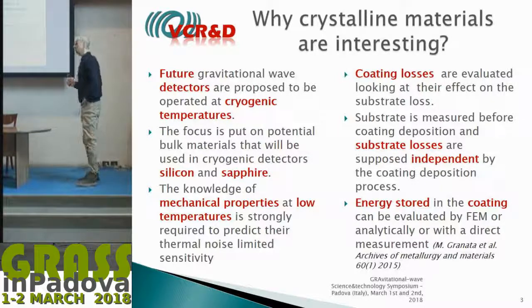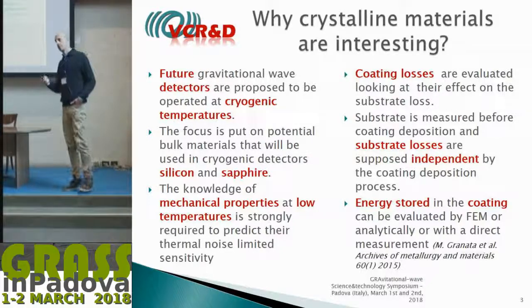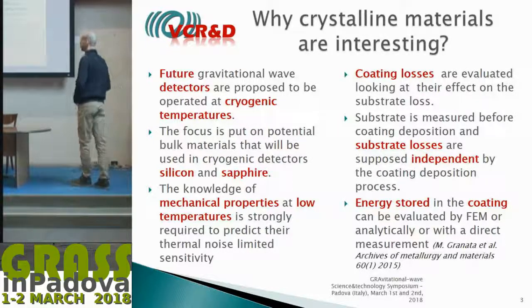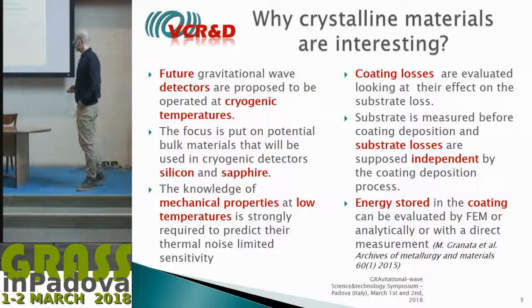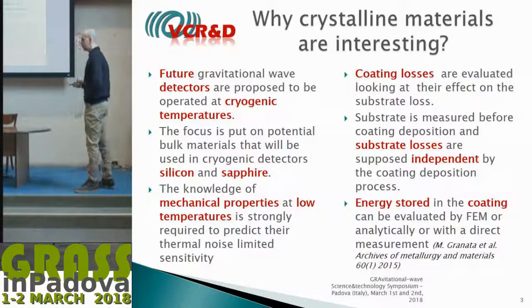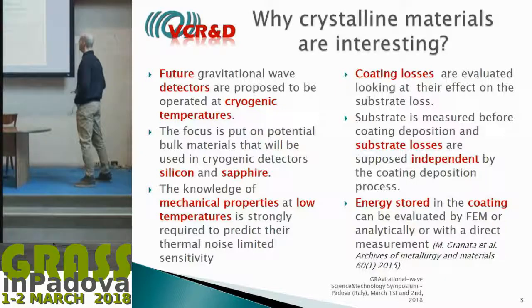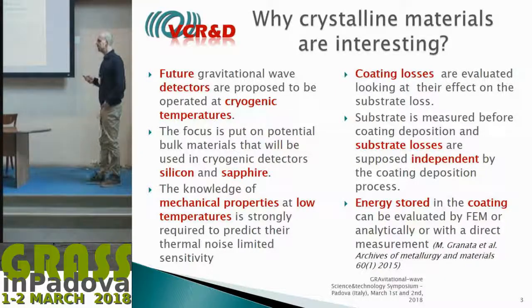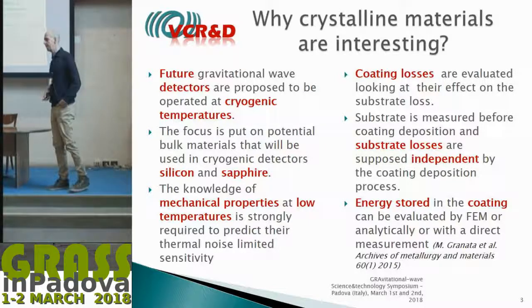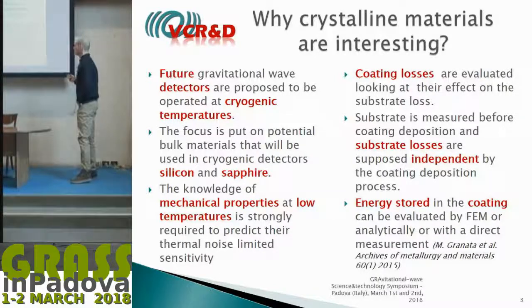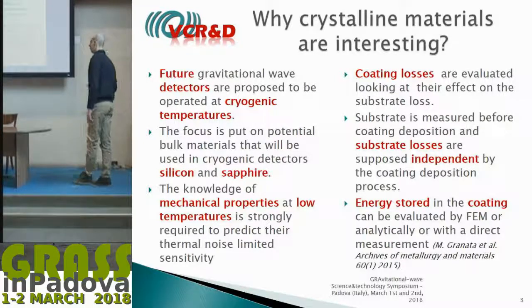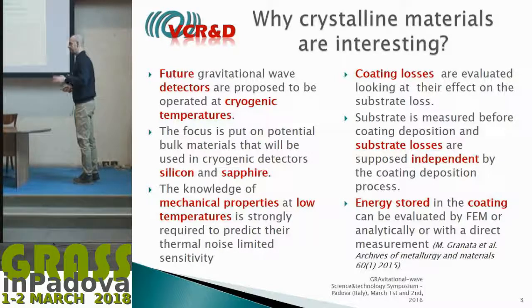What we usually do is look at the effect on the loss of substrates. We have to know very precisely the loss of the substrates we are using in order to work out the coating loss. We assume the substrate losses are independent of the coating deposition, but this is not the case for thermoelastic damping. We also have to evaluate the energy stored in the coating with respect to the total energy of the sample, which can be done by finite element analysis, analytically, or by direct measurement of the frequency shift after coating deposition.